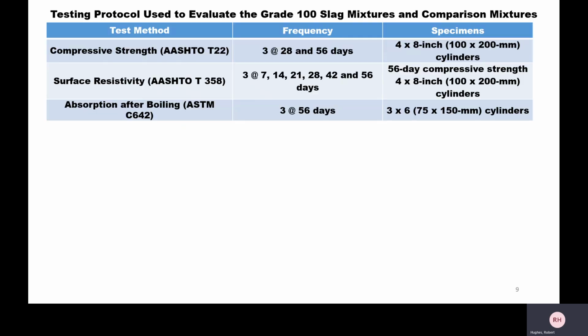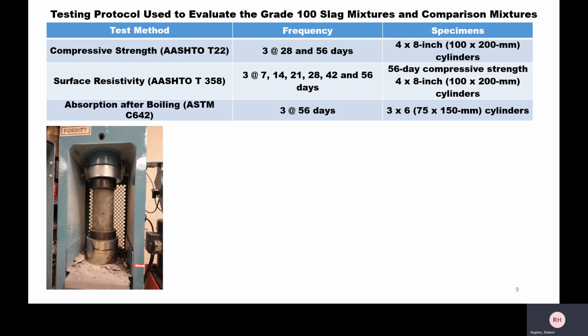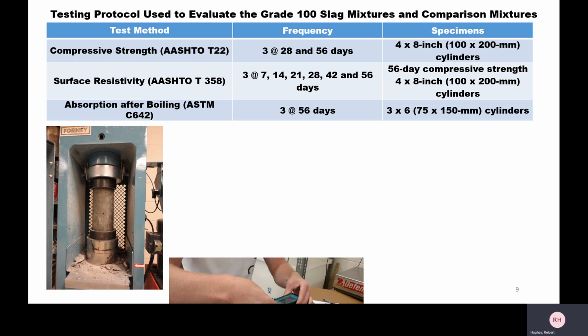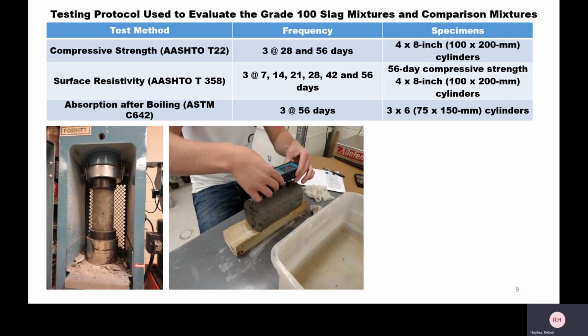I'll get into some of our testing protocols. The three tests we use, like I said, are compressive strength, SR, and absorption after boiling. Compressive strength was tested at 28 and 56 days. We had three 4x8 cylinders tested at those intervals in accordance with AASHTO T22. SR we tested a lot more, because that is our judgment of permeability of the concrete. So we do three cylinders at 7, 14, 21, 28, 42, and 56 days, which is okay because it is a non-destructive test method. Like I said, it measures the permeability of the concrete. And absorption after boiling is a measure of porosity. We do that at the end of the cycle at 56 days. We use three of our 3x6 cylinders for that.